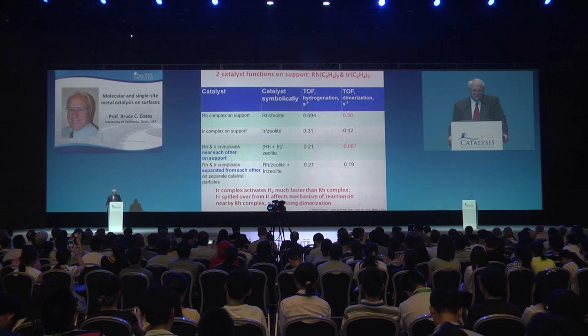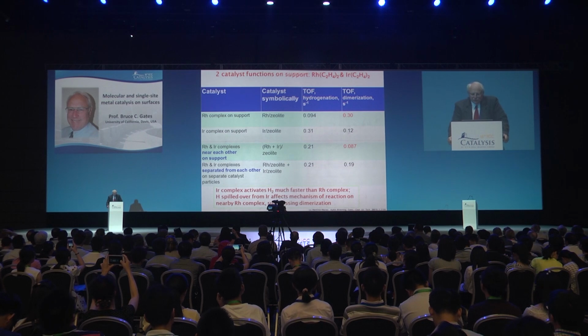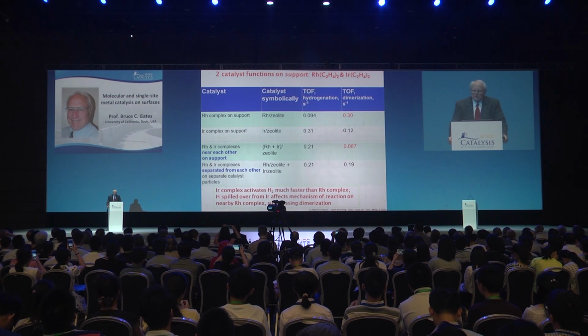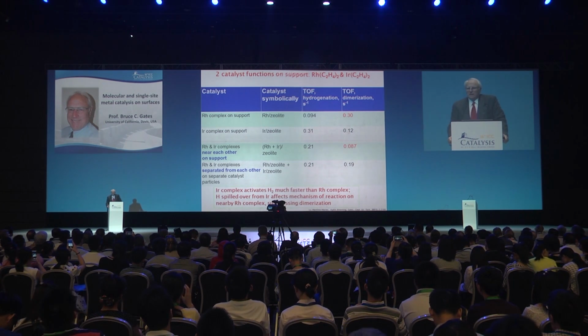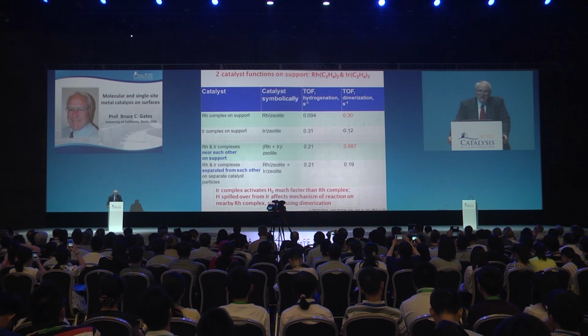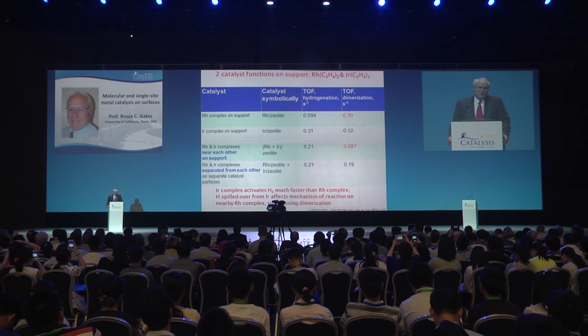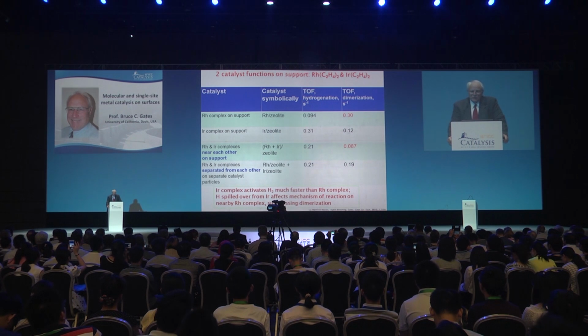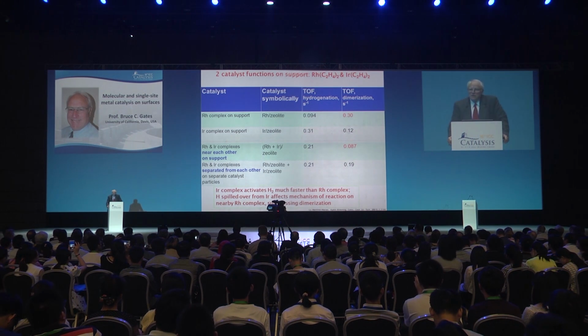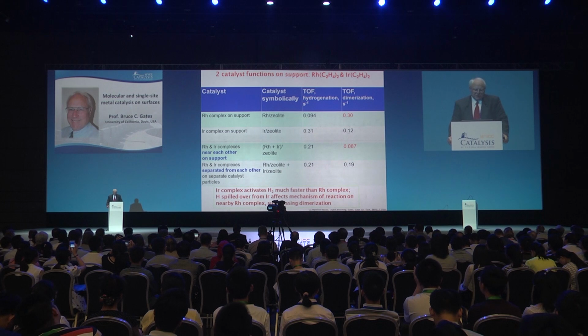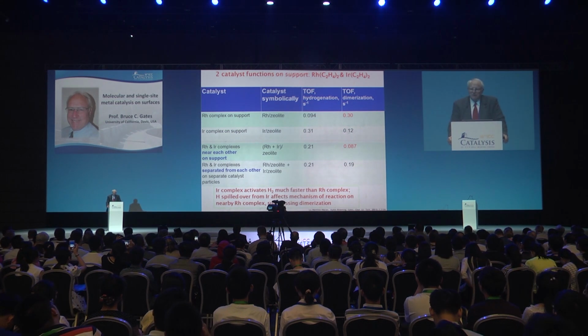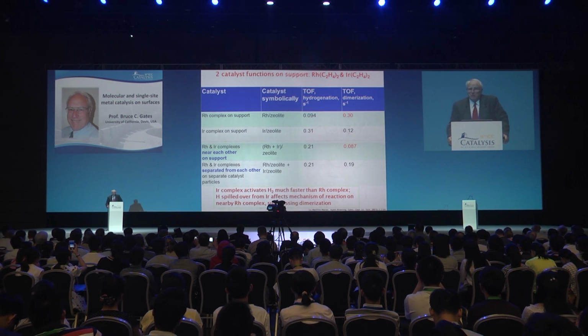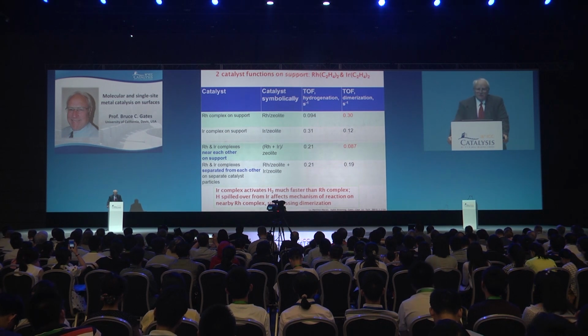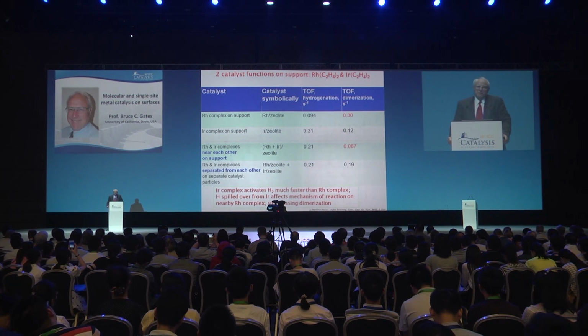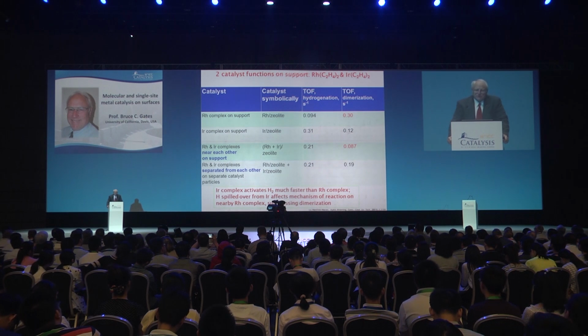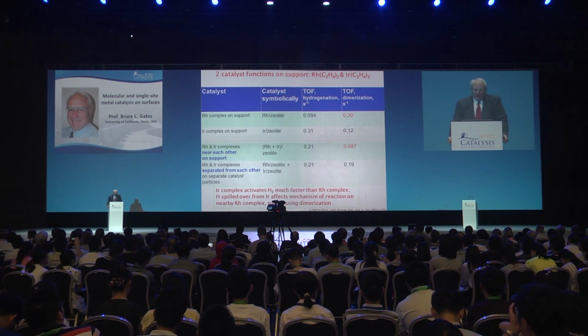So here's what's familiar: the zeolite-supported rhodium diethylene complex, and in the same zeolite, the supported iridium diethylene complex. We've done the obvious experiment of putting those two metal complexes in separate particles of catalyst and using them in the same reactor. In that case, the result's just kind of trivial—you get the average performance from the two catalysts.